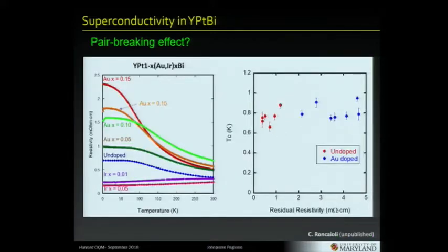What happens in yttrium platinum-bismuth? Well, this came out of a study where we were actually trying to dope the system, but it turns out it's not really doping it, but, at least experimentally, it's increasing the resistivity. So putting in gold into the system, we can go from this undoped behavior up to almost 4 or 5 times the residual resistivity. Amazingly, when we do that, we have no change in TC that we've measured so far.